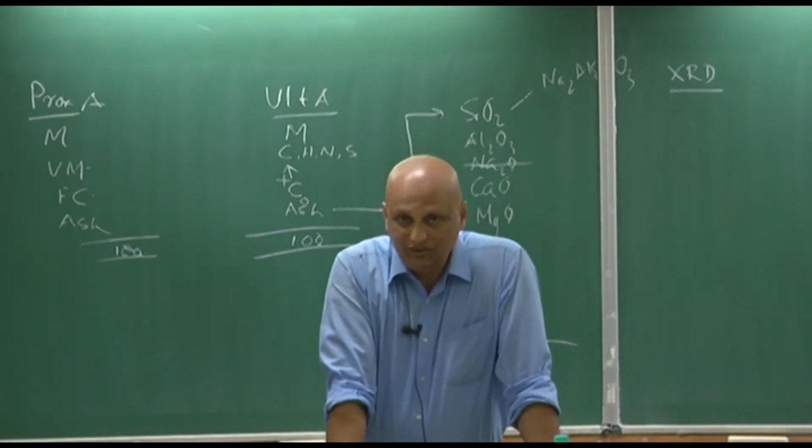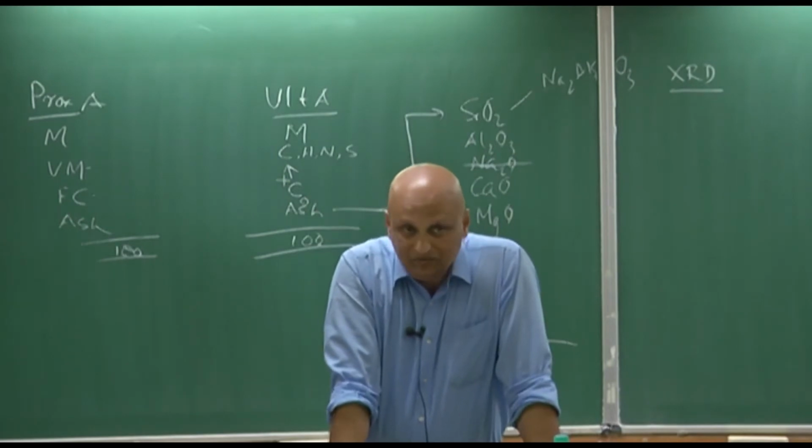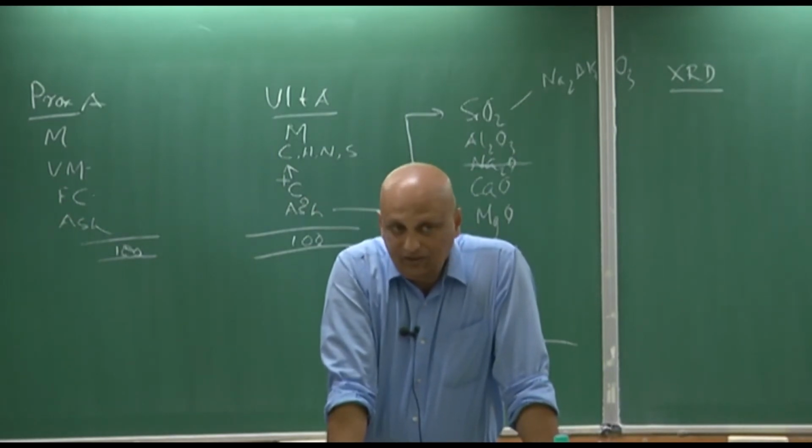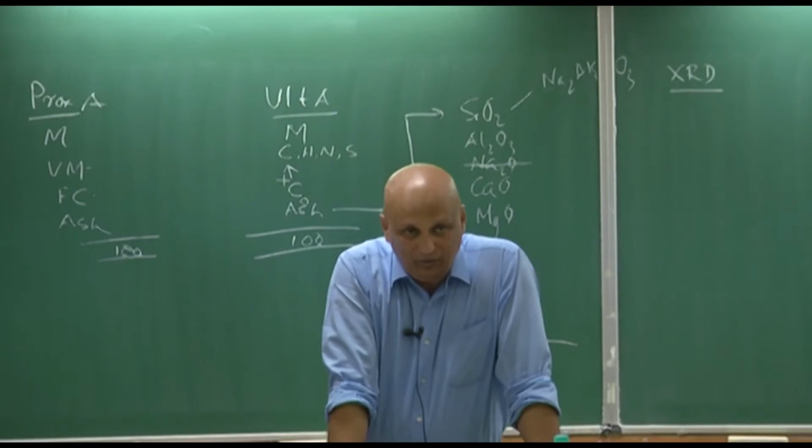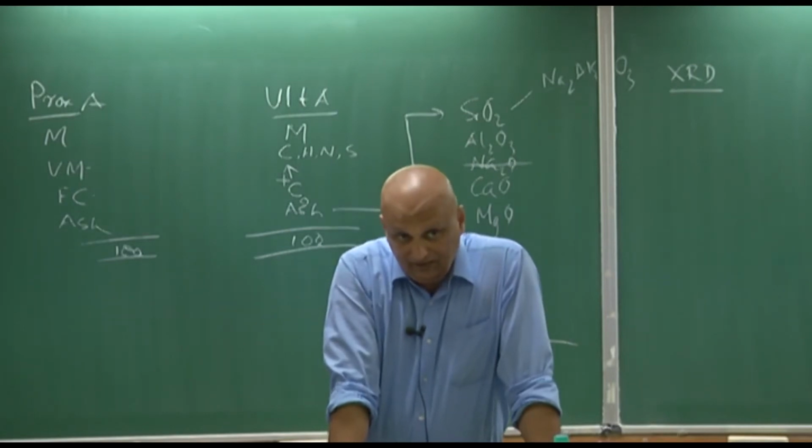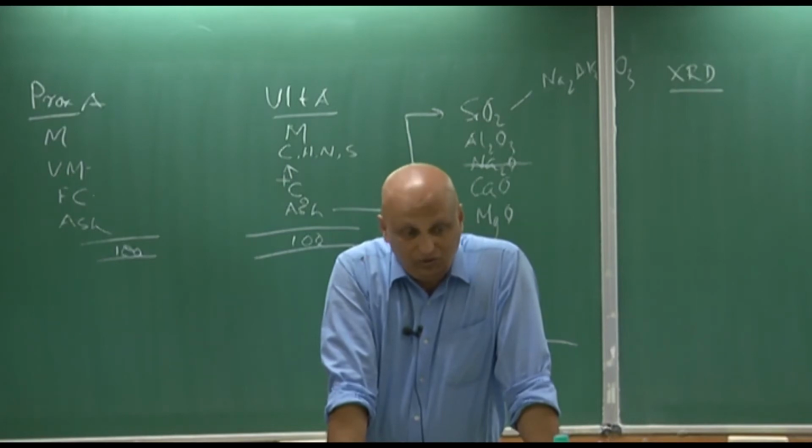So there is a standard, a worldwide standard, and an Indian standard as well, that you do it at 900 degrees centigrade for 7 minutes in closed crucibles.